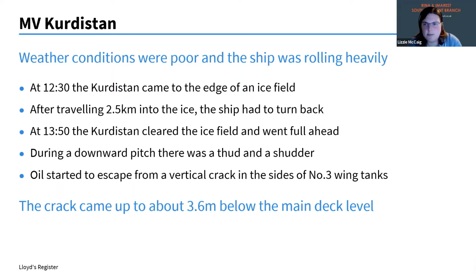As she cleared the ice field, the crew heard a bit of a thud, a bit of a shock, and oil started to leak from a vertical crack in the sides of the number 3 wing tanks. And these cracks came up to about 3.6 meters below the main deck level. So they're quite big cracks.